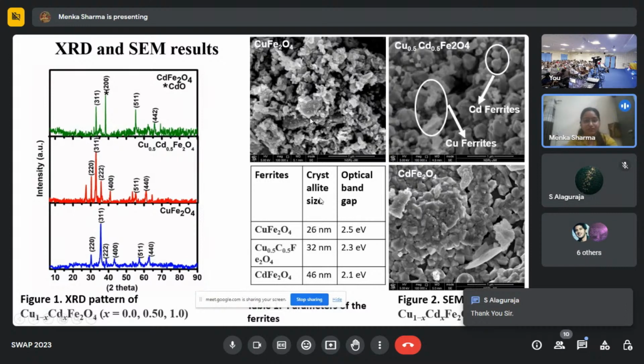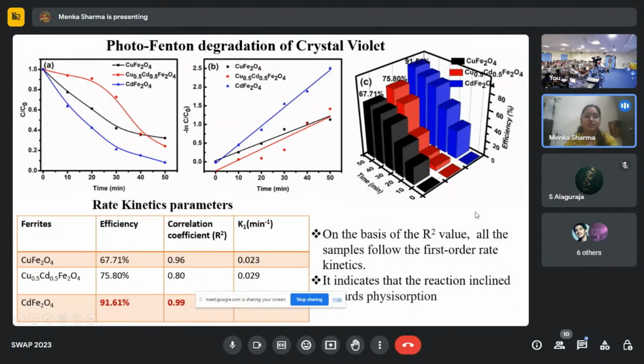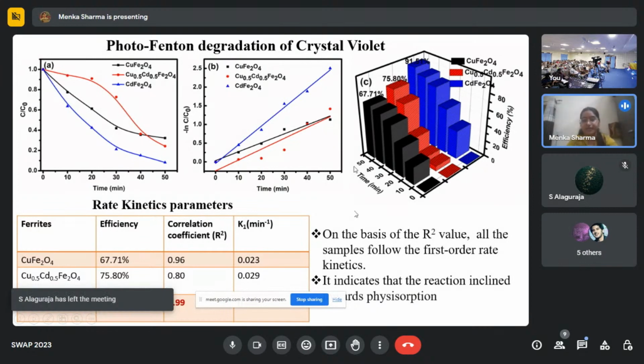The optical band gap was calculated from UV spectroscopy, and the band gap decreases as we move from copper ferrite to cadmium ferrite. I have performed the photo-Fenton degradation over two cationic dyes. One is crystal violet and the other one is malachite green.